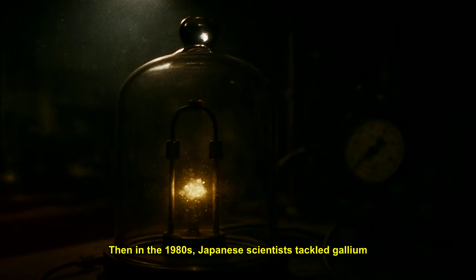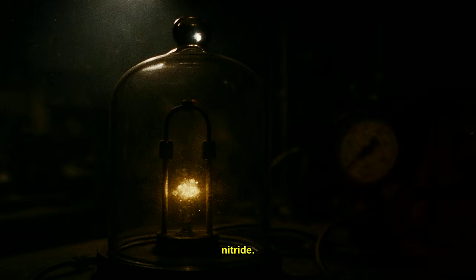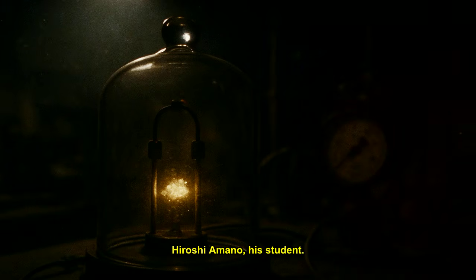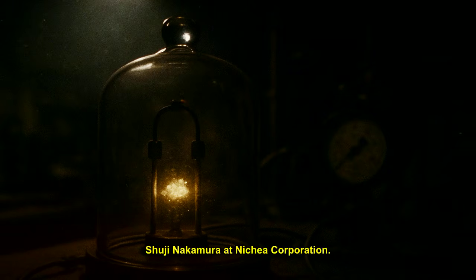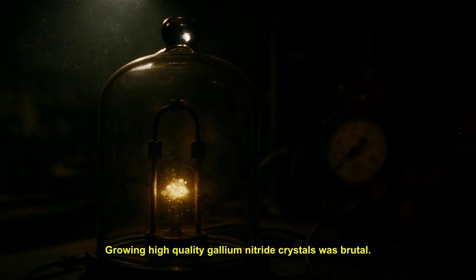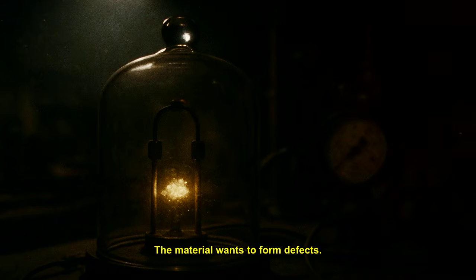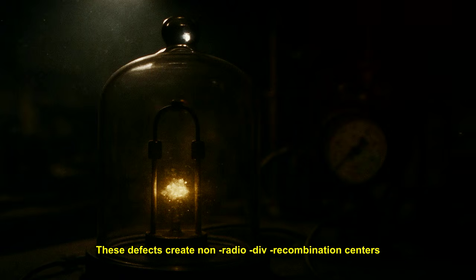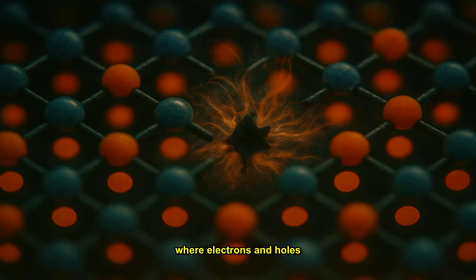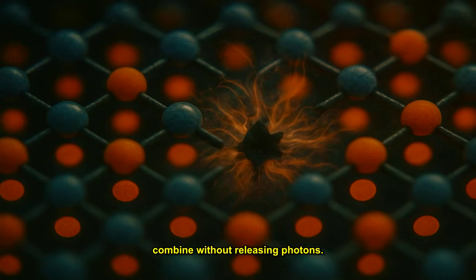Then, in the 1980s, Japanese scientists tackled gallium nitride. Isamu Akasaki at Nagoya University, Hiroshi Amano, his student, Shuji Nakamura at Nichia Corporation. Growing high-quality gallium nitride crystals was brutal. The material wants to form defects, impurities, crystal dislocations. These defects create non-radiative recombination centers where electrons and holes combine without releasing photons.